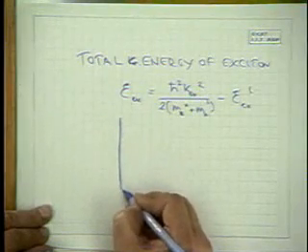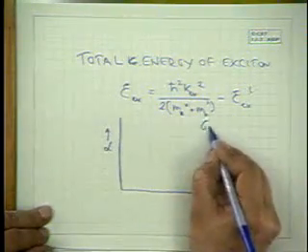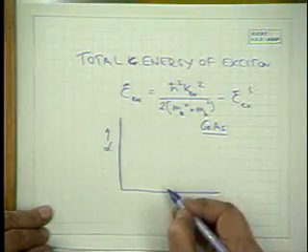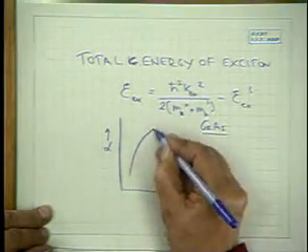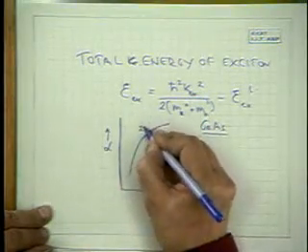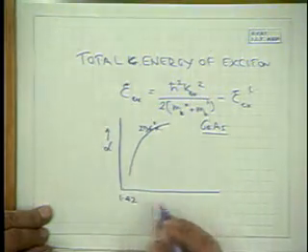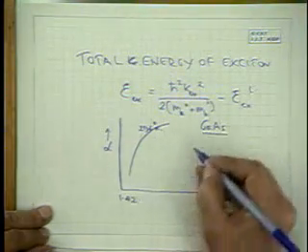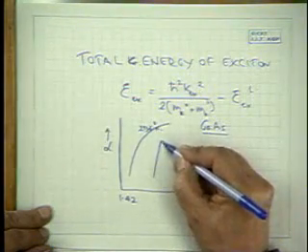And as I'll show experimentally, what does this give rise to? That we have a very pure semiconductor at low temperature. Take the case of gallium arsenide at 294K, one has a characteristic absorption edge without any special features. As we know that the band gap increases as we go down in temperature, at 78K we have a little structure like this.